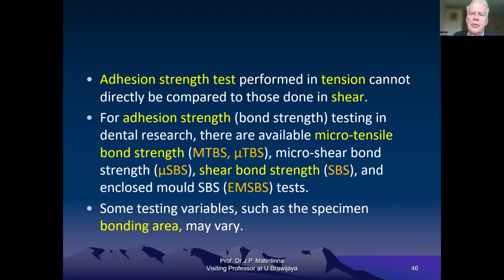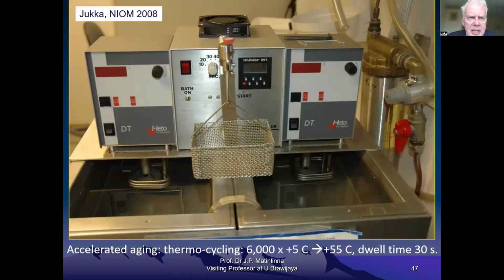However, adhesion strength tests performed in tension cannot be compared to those done in shear. And if you decide to measure adhesion strength, there are a few available ways to carry it out: microtensile bond strength, micro shear bond strength, shear bond strength, and enclosed mold shear bond strength. Some testing variables, such as the specimen bonding area, may be very different. This device is showing how we artificially can age specimens. We have two water baths, cold and hot, and the specimens are in a basket, and then they are transferred back and forth, as long as possible. This is a thermocycling unit.